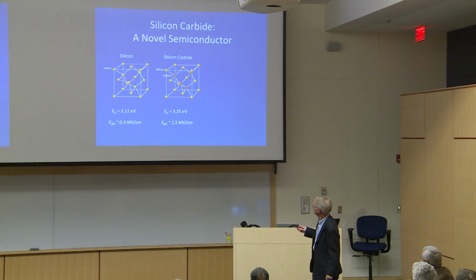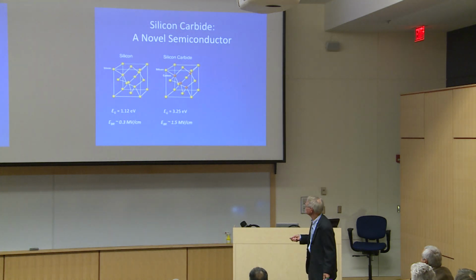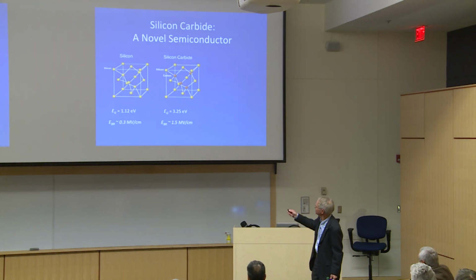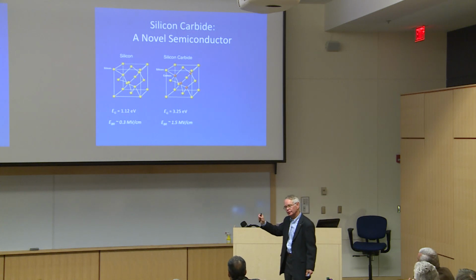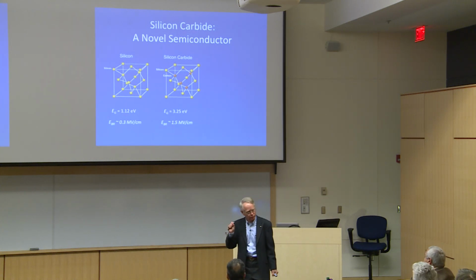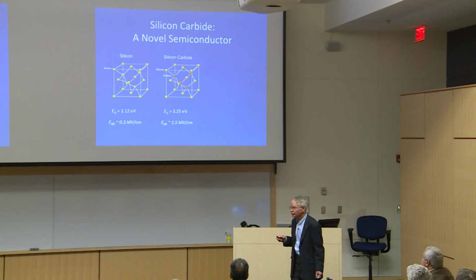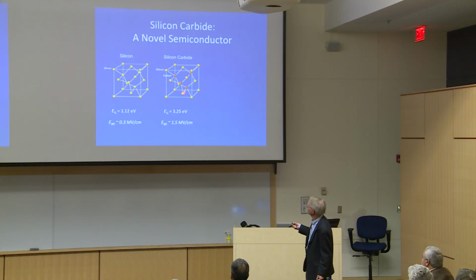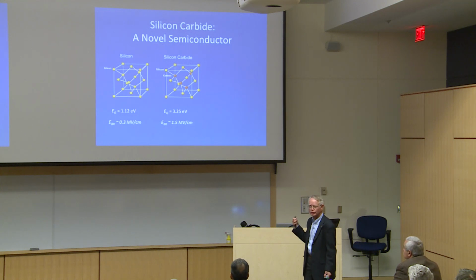In silicon carbide, the breakdown field is about 5 times higher. Now, for power devices, that's very important, for power switching devices. And the reason it's important, and I won't go through the details, is that as we build a power switching device, there's a figure of merit that we are always concerned with, and that figure of merit scales as the cube of the breakdown field. So a factor of 5 turns into a factor of 125. So the same device in silicon carbide would have a figure of merit that was over 100 times better than silicon. That's the reason that there's been so much interest in silicon carbide as a semiconductor.